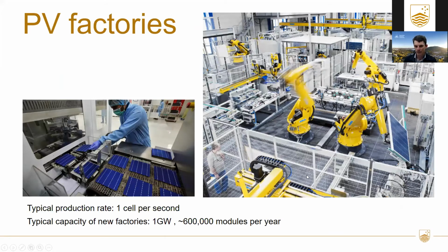So when it comes to PV factories, what we're seeing now is that these are very highly automated facilities. Typically we're making solar cells around about 156 by 156 millimeters, producing a few watts of power. A typical factory would be churning these through at roughly the rate of one per second. So very high throughput of these relatively large area devices.